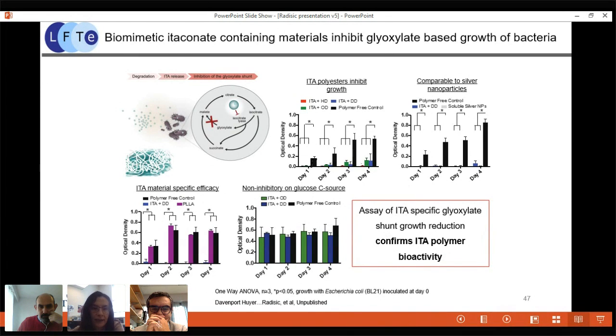In addition to that, we can see that our controls such as PLA or even PLGA, these additional controls that we did that are not shown here, do not exhibit any kind of bacterial growth inhibition. However, if we use non-inhibitory glucose source of carbon, then we don't see any differences, which still, again, tells us that these effects are due to itaconate.